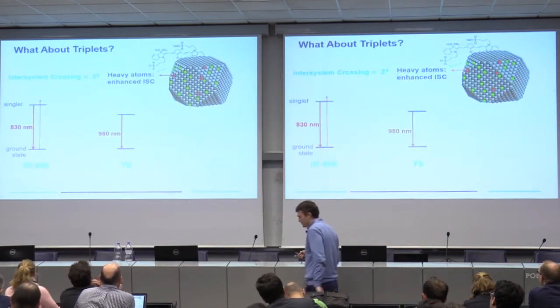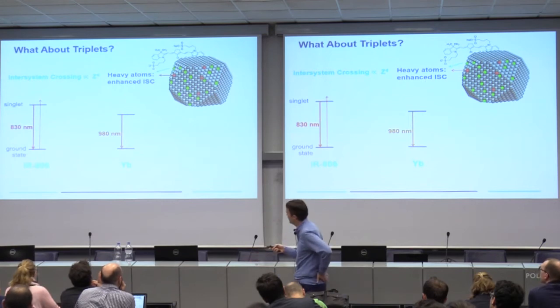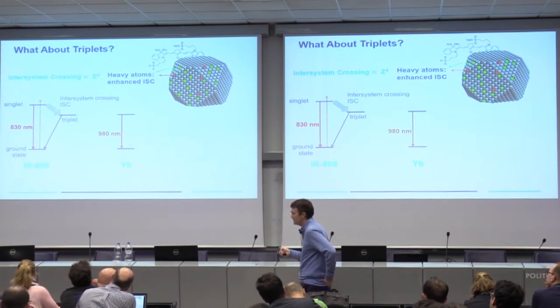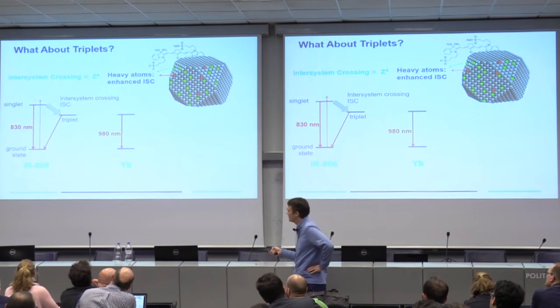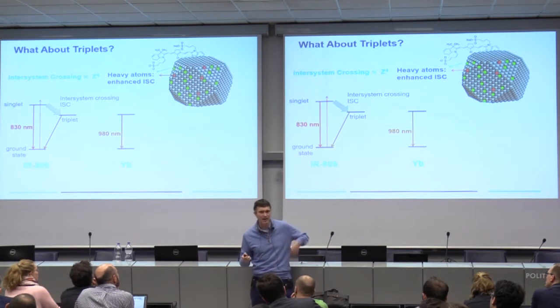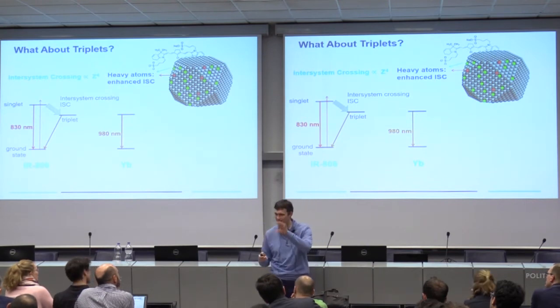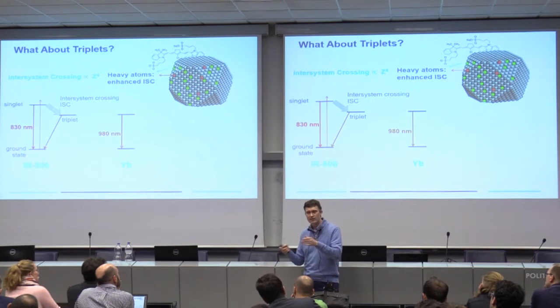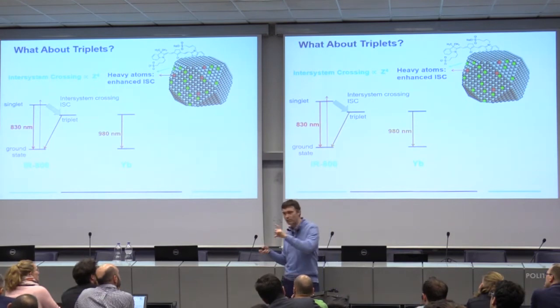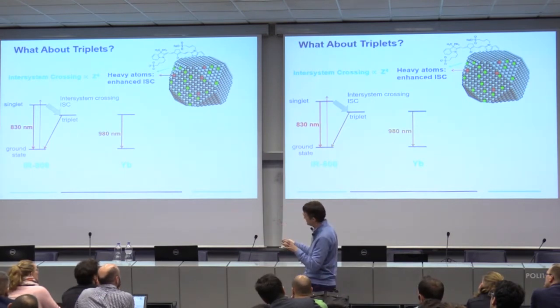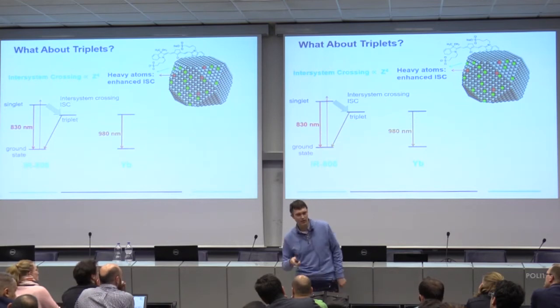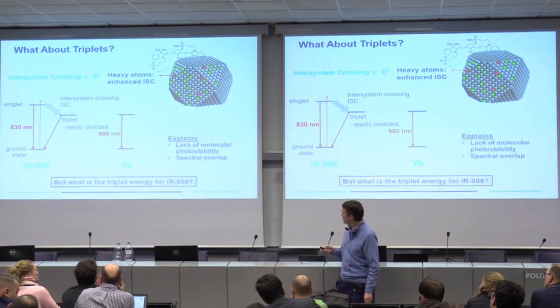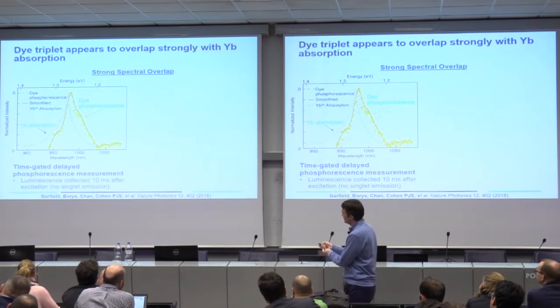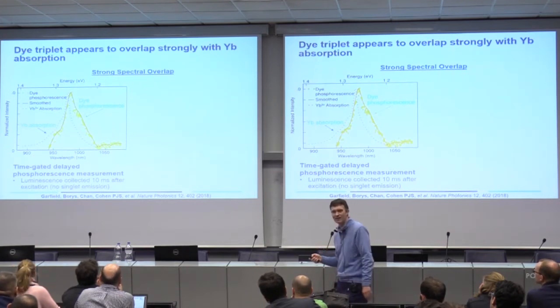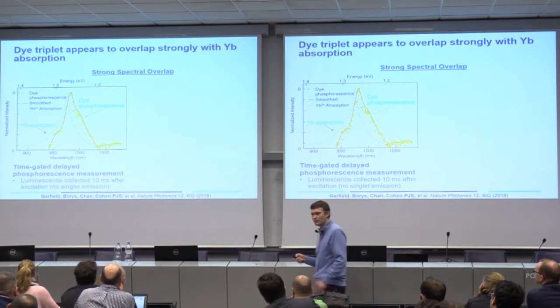I'll save you all the details, but what essentially we realized is that actually the energy transfer isn't occurring through this so-called singlet level of the dye molecule at all. What's happening is when the dye molecule gets close to the heavy atoms, the lanthanide atoms in the nanoparticle, there's some spin scattering, you get a spin flip, and the dye molecules almost instantaneously go to the so-called triplet state, which is at a slightly lower energy. And we were able to figure out where that triplet energy lies, and it turns out it lies almost right on top of the ytterbium absorption. So this was pretty exciting.